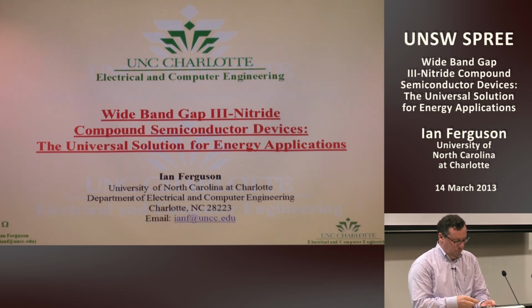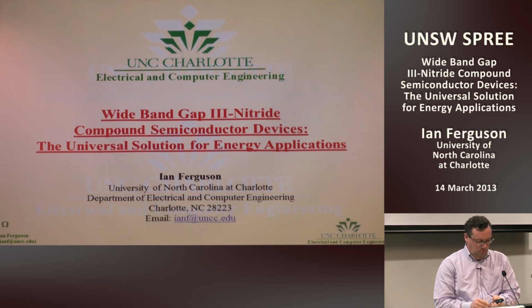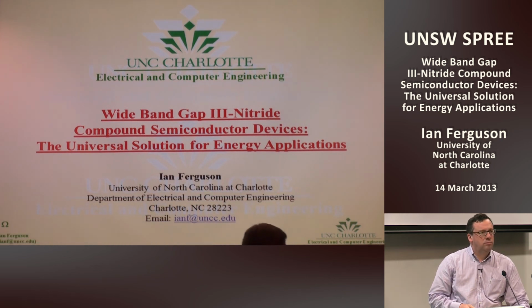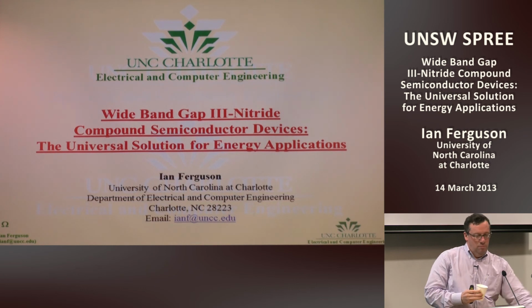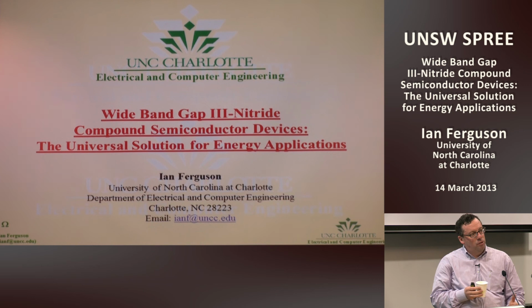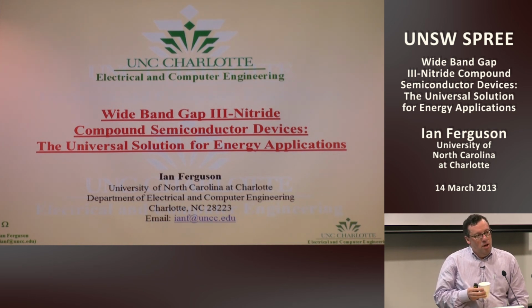Yeah. So I take it from your presentation, I wasn't quite clear on this point, that you grew these exclusively by MOCVD? By MOCVD. Not by ALD? Not ALD. The ALD was for transitional layers on some substrate technologies. All the growth was done by MOCVD. Typically, MOCVD is used for higher quality optical materials, but if you give me an MBE tool, I can use an MBE tool, it doesn't matter.